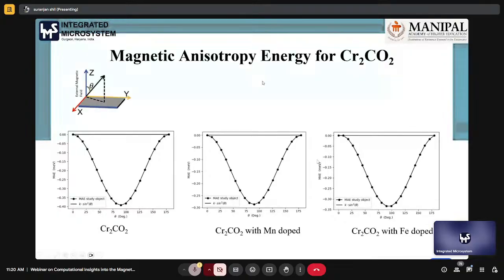Those are ferromagnetic. And then the magnetic anisotropy energy for chromium carbide with oxygen termination. If we calculate the magnetic anisotropy behavior, we can see here that all have the in-plane anisotropy. This is undoped, this is manganese doped, this is iron doped, and we did not do it for the cobalt dope because it's antiferromagnetic. So we only do it in the case of ferromagnetic materials.